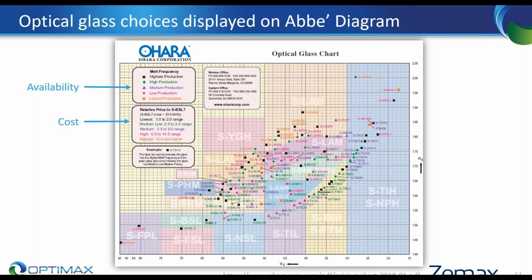SBSL 7 is a borosilicate glass. It is optically equivalent to NBK7. And as many of you are also aware, BK7 or SBSL 7, they're the workhorse of the optics industry, and fairly benign in terms of properties, both mechanical and chemical, and they're pretty much middle of the road optically as well. So it's a really great material. Also one of the cheapest materials and highest production. Moving away from that tends to change the optical properties to a slightly less desirable state, which I'll mention later, but it's also a good baseline for cost.